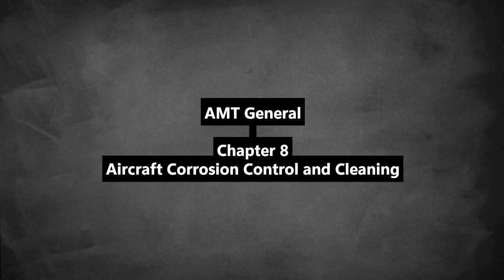And dissimilar metal corrosion, galvanic, we touched on that, where different metals meet with moisture if the insulation fails. Yep. Can be hidden, can be serious. And it's not just design contacts. Your source wisely points out using steel wool or steel brushes on aluminum or magnesium is a bad idea. Tiny steel particles get embedded, create galvanic cells. Same risk with some abrasive pads if you're not careful about cross-contamination.